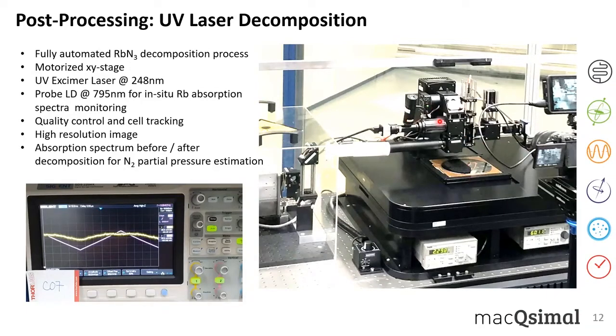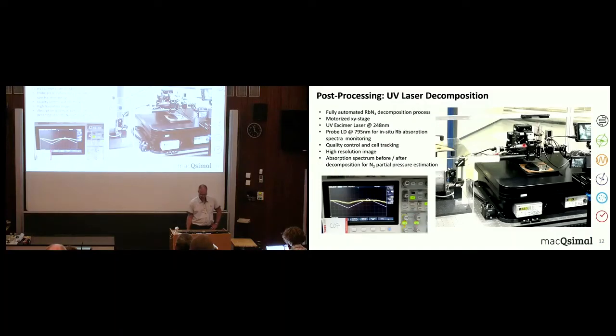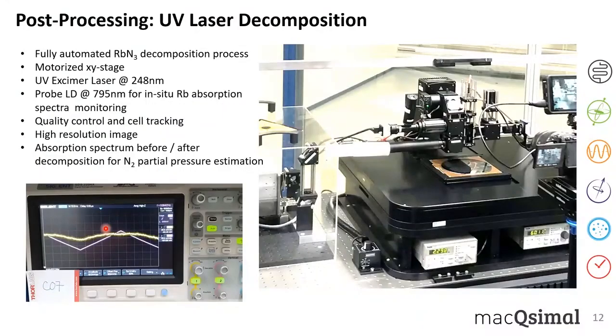Here we have a laser diode which emits light at 795 nanometer, and which is used to make in situ measurement of the rubidium absorption. What we do here is ramp the current of the laser, which changes the wavelength of the light, and as soon as you are on the right frequency for the rubidium atoms, you see a spectral line width that appears.